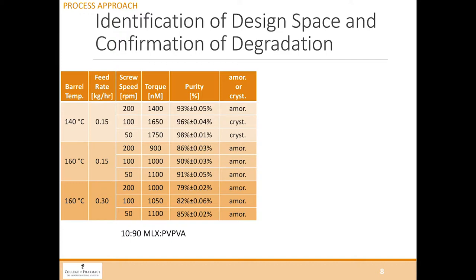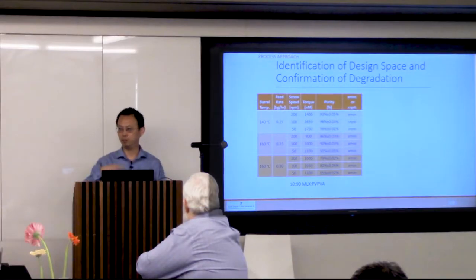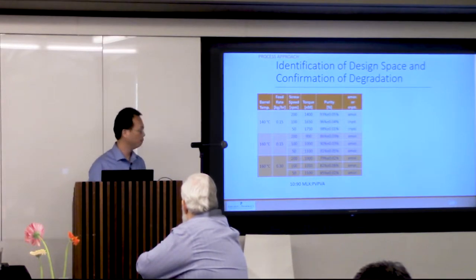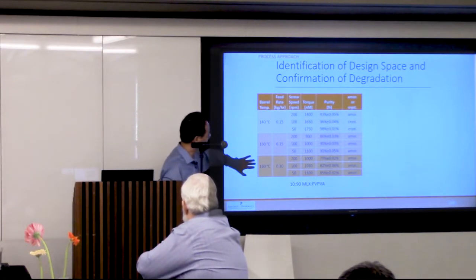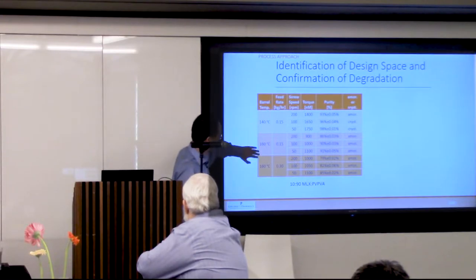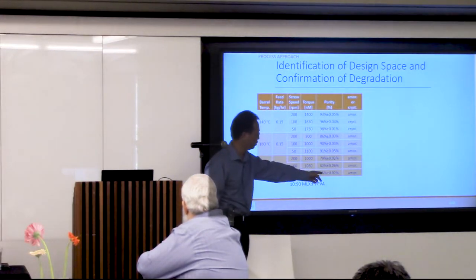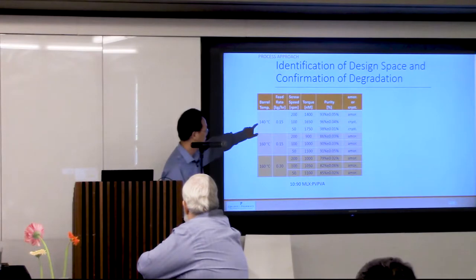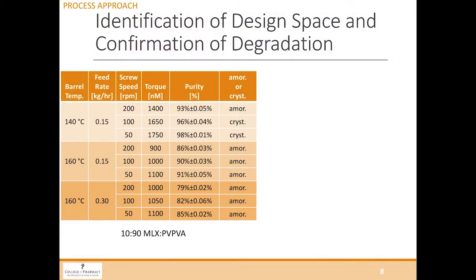It's like in plastics, when they run metric tons per hour, they would need the barrel heated at the very beginning. But once the process is going, you can turn off the barrel. The machine runs on its own. Okay? Because the mixing itself creates so much heat. And from this one, you can tell, when we go to high temperature, we get amorphous material, but we start seeing a lot of degradation. At 140 degrees, you would find a sweet spot. Okay. You can play with different screw speeds, and you can dissolve the drug without creating too much degradation.